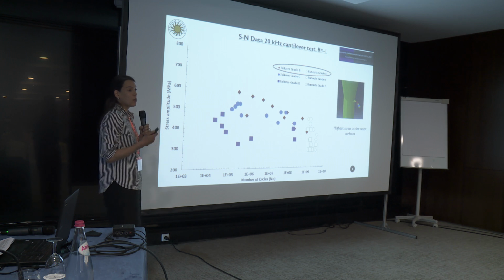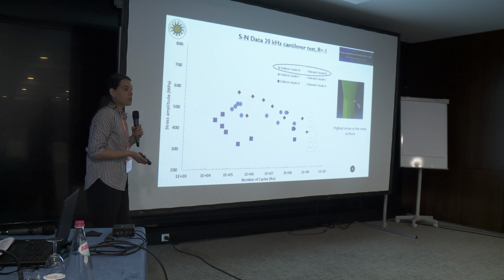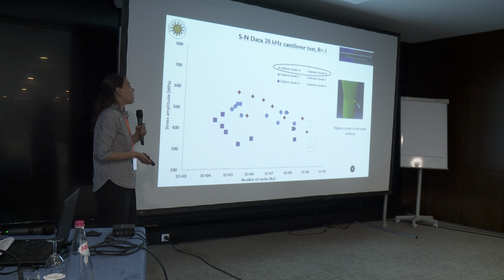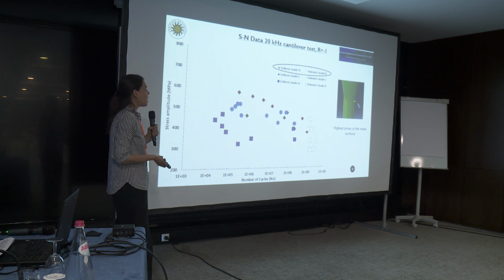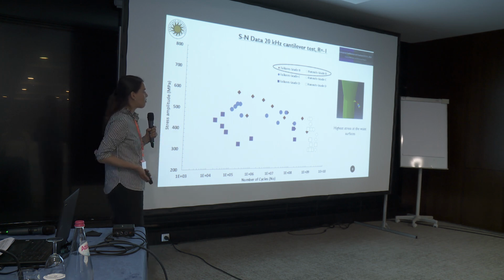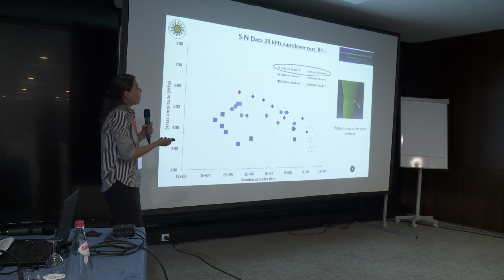Approximately, we tested 20 specimens for each grade, so we are speaking about 60 fractured specimens. All of them fractured in the waist area, as predicted by our FEM stress calculations.